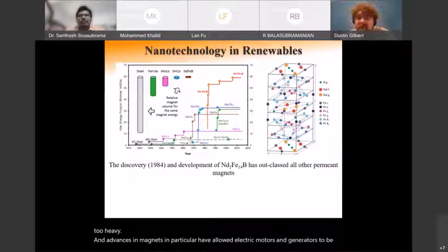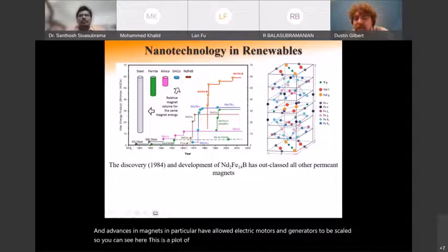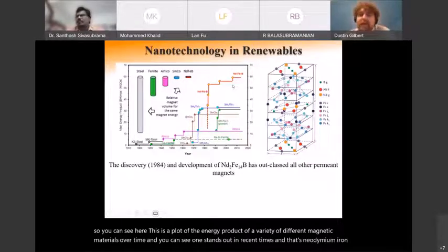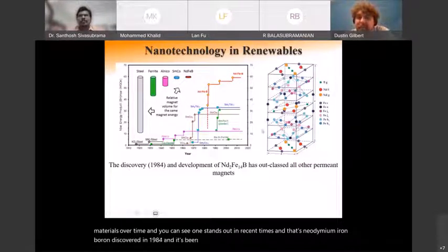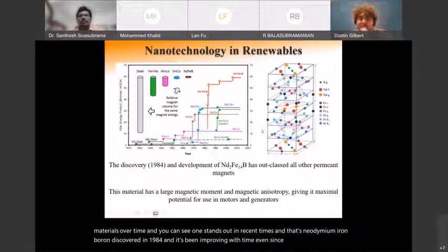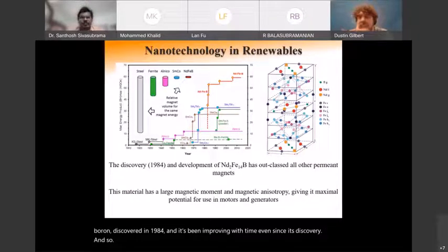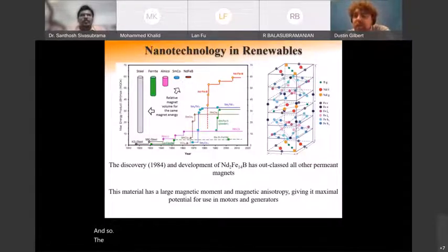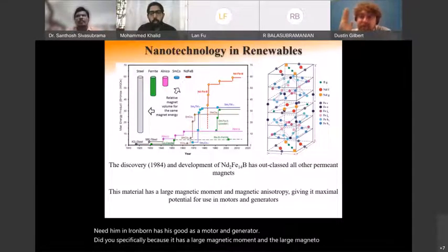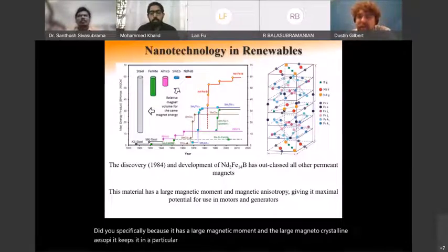So you can see here, this is a plot of the energy product of a variety of different magnetic materials over time. And you can see one stands out in recent times, and that's neodymium iron boron, discovered in 1984. And it's been improving with time, even since its discovery. And so neodymium iron boron is good as a motor and generator material, specifically because it has a large magnetic moment and a large magnetocrystalline anisotropy, which keeps it in a particular orientation, even when it's in a magnetic field.